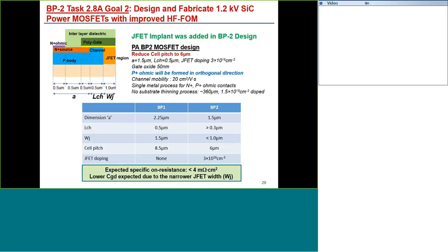In terms of the second task in BP2, to make devices with improved high-frequency figure of merit, our approach is to add a JFET implant, which was not there in the previous design. There's a JFET region, but not an enhanced doping in the BP1 devices. By increasing the JFET doping, we can reduce its width, WJ, in the cross-section. And by doing that, you can reduce the cell pitch.